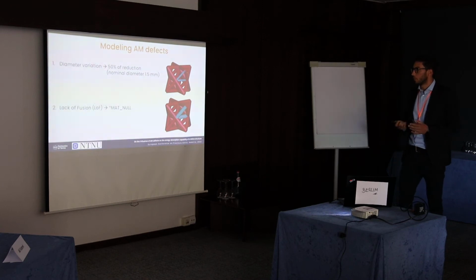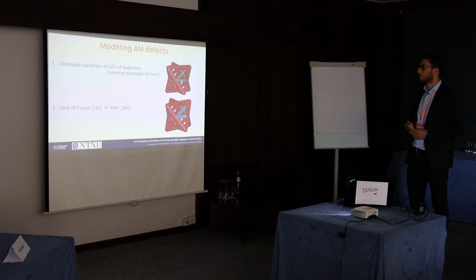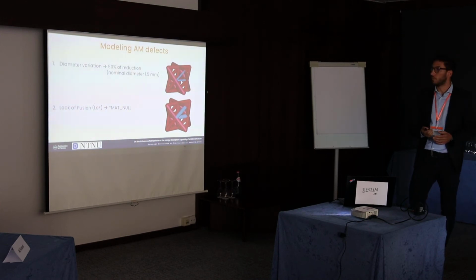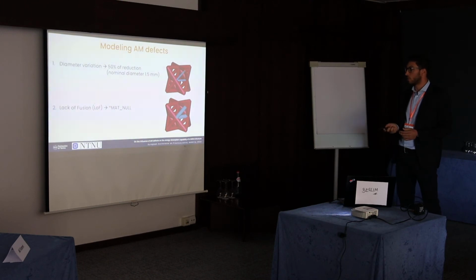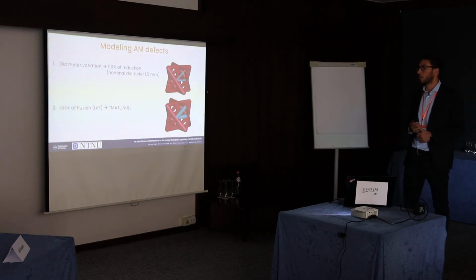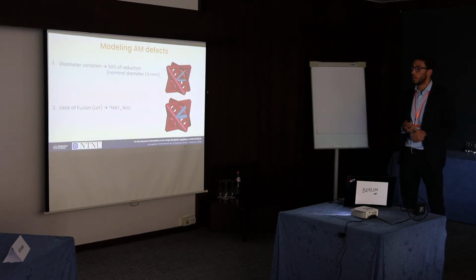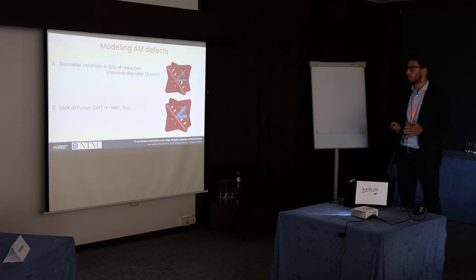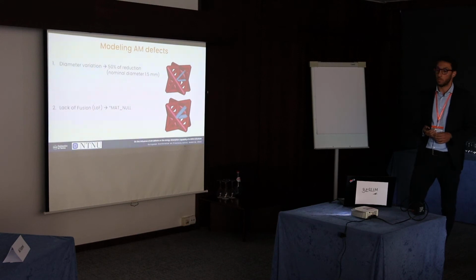So once we validated the finite element model, we decided to investigate the effects of some additive manufacturing defects. In particular, we considered two defects. The first one is a variation of the diameter, and we considered a 50% reduction with respect to a nominal value of 1.5 millimeters.